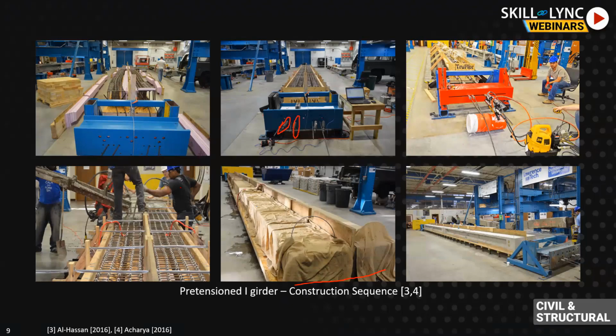So what we do when we pour concrete at this stage, we make some samples, some concrete cylinders, and then we cure them, and then we break that cylinder. Once we make sure that the concrete is okay, it has attained initial strength, then we cut it. And after we cut it, you can see we demold it.